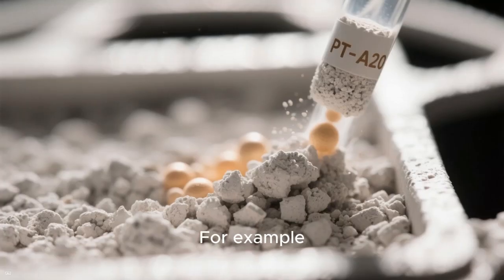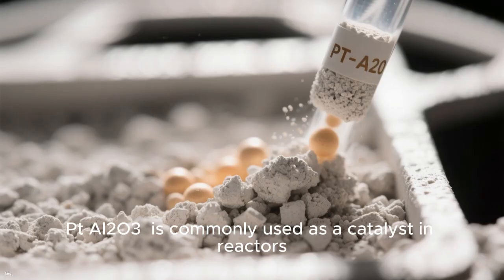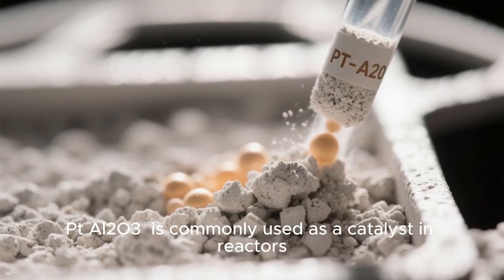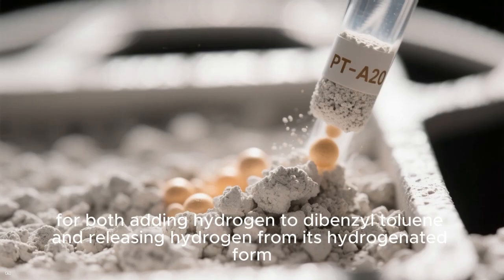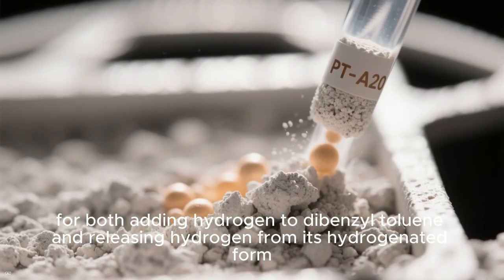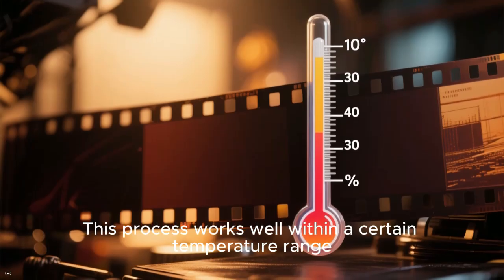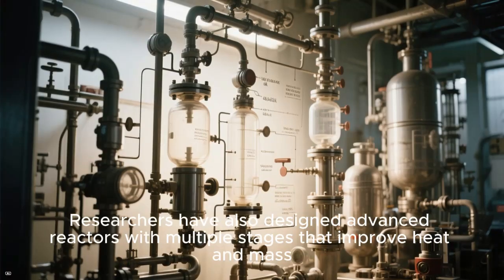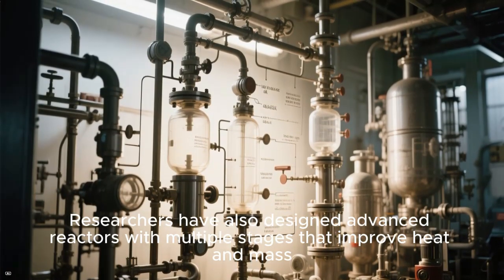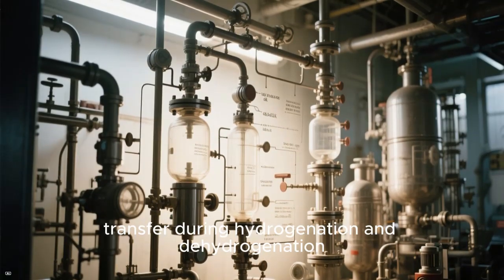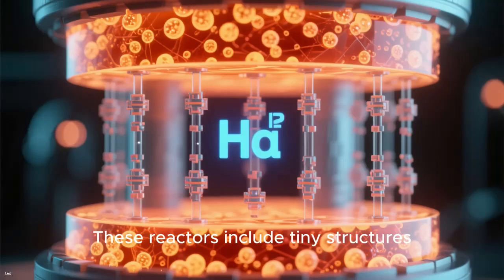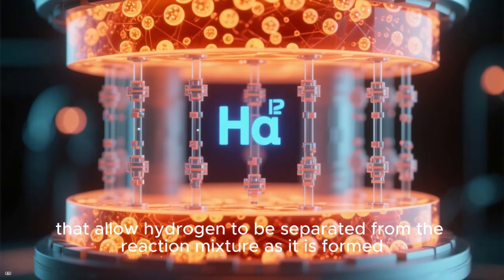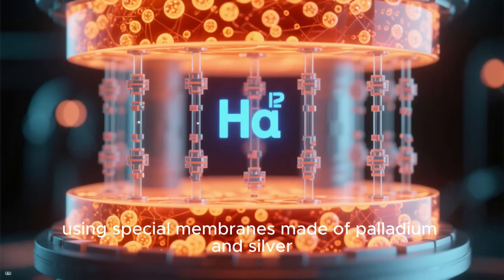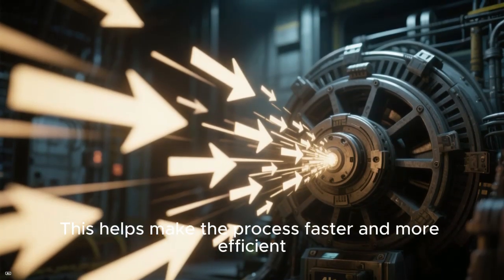This means hydrogen can be added and released in one system, which simplifies the process and can make hydrogen storage more efficient. For example, platinum supported on aluminum oxide (Pt/Al2O3) is commonly used as a catalyst in reactors for both adding hydrogen to dibenzyl toluene and releasing hydrogen from its hydrogenated form. This process works well within a certain temperature range, typically around 290 to 310 degrees Celsius. Researchers have also designed advanced reactors with multiple stages that improve heat and mass transfer during hydrogenation and dehydrogenation. These reactors include tiny structures that allow hydrogen to be separated from the reaction mixture as it is formed using special membranes made of palladium and silver. This helps make the process faster and more efficient.